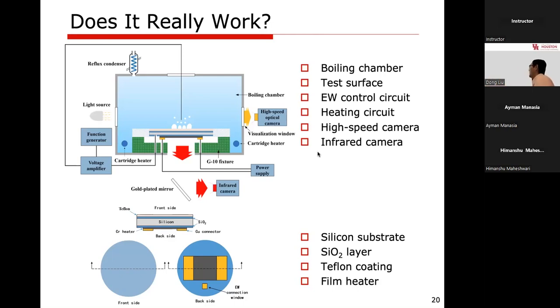Now for the measurement, we have two circuits: one to control the signal for electrowetting, and the other one to power the heater. Now for measurement, we have a high-speed camera to monitor the bubble dynamics. So we want to see how the bubble motion will be affected by electrowetting. And also we have a high-speed infrared camera. So we are concerned with temperature. So we want to dissipate, let's say, 500 watts. But how does the temperature change? We do not want the temperature to be so high that the silicon wafer be damaged. So by the way, when we exceed the CHF, we actually observe the cracking of the silicon wafer. It was a mess. All right. So these are the experimental methods.